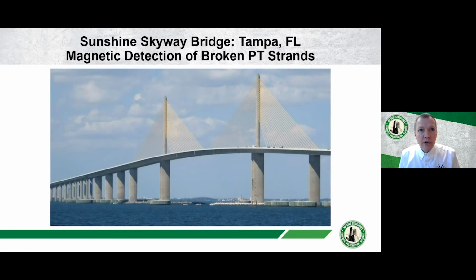There are cases where you may want to know the condition of the strands themselves. It may be grouted. You may not have any presence of voids, or you may not be aware whether there are or not. There is a technique available using magnetic flux that can be used to determine if you've got broken PT tendons, or more likely broken individual strands or wires. And I'm just going to show you a slide or two from a project that we did on the Sunshine Skyway down in Florida. The post-tension tendons in question here are transverse post-tensioning that's in the deck of the bridge.